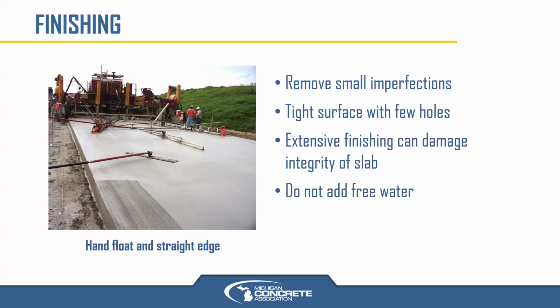The more we manipulate that surface, we're not necessarily making better concrete. So what I recommend to people is consolidate and strike off. That paver is doing, in this example, a lot of that work with a machine, which is good. But regardless of whether you have a paver or other types of equipment, consolidate it, strike it off. In this case, they're going for ride quality. So they've got that long straight edge on a handle to try to cut off bumps and see if there are any dips as they move the straight edge from side to side across that lane or 2 lanes that they're paving. And that's fine.